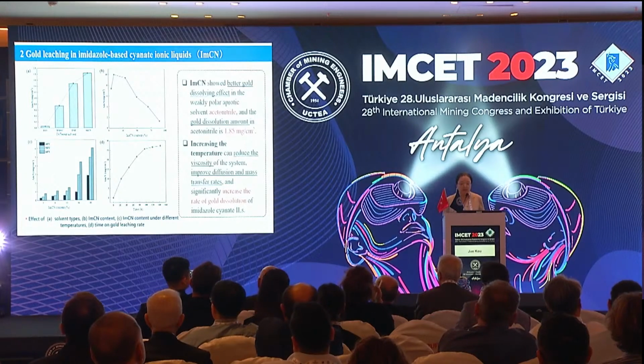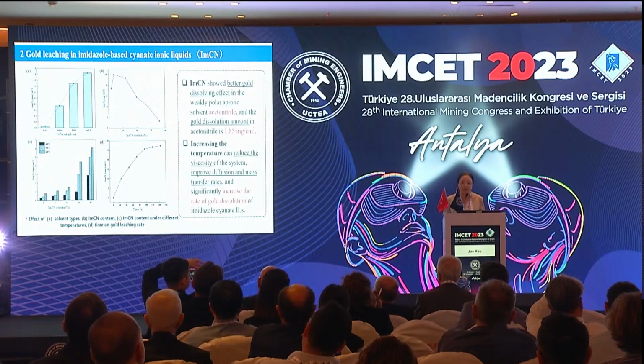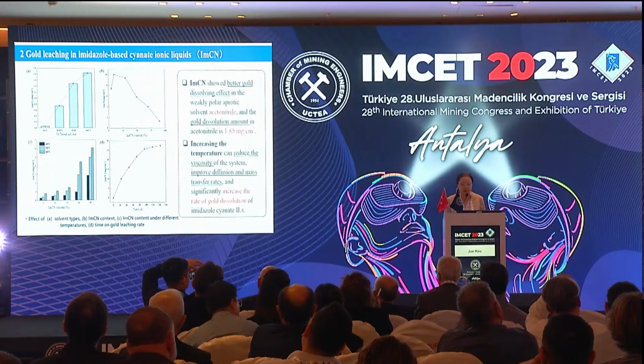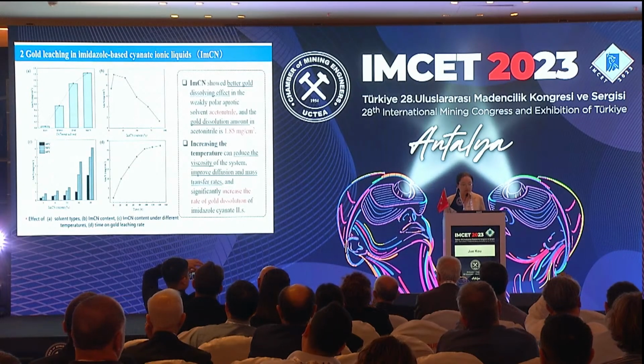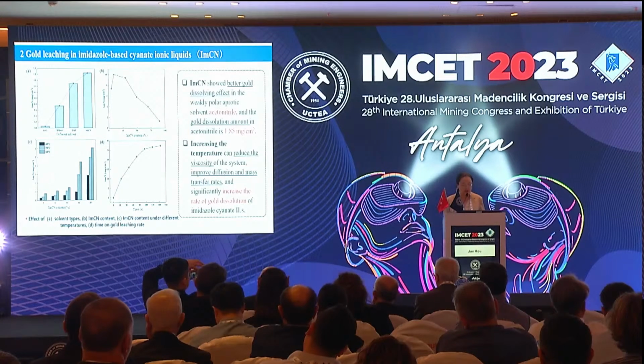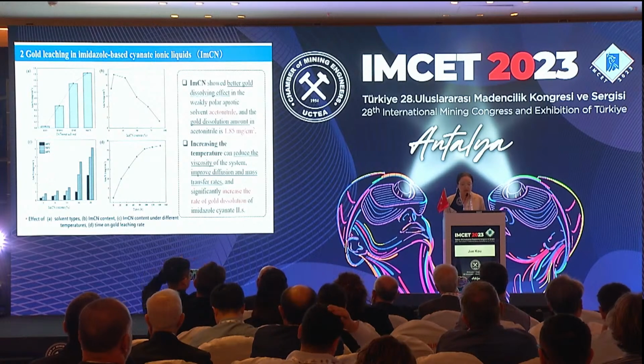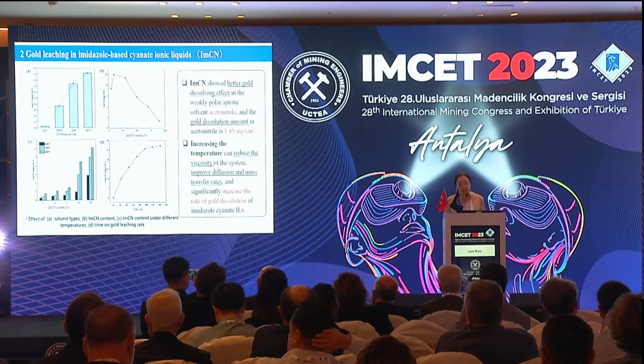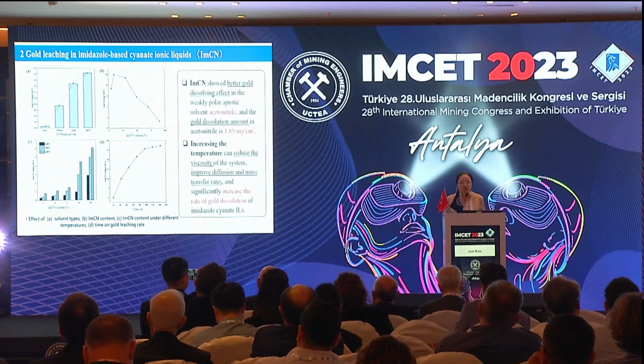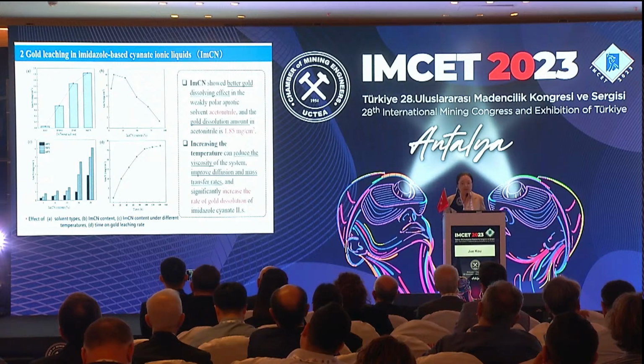We've tried the IMCN to see if it can have a good performance in gold leaching with the CPU pins. And here we tried 4 different solvents. We tried different contents, different temperatures, and different storing times. And it shows us that a high content of IMCN might result in high viscosity of the system. The high viscosity will decrease the leaching rate. Therefore, the better content for IMCN in leaching is about 20%.